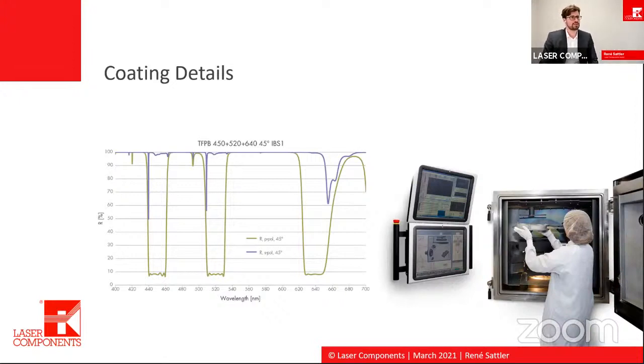We designed the coating for an angle of incidence of 45 degrees, so it's pretty easy for the customer to handle this component. The customer did not want a big displacement of the transmitted beam, so he wants the substrate pretty thin. As we applied an IBS coating with lots of stress, we also had to apply a stress compensation coating on the backside to maintain the good surface figure of the substrate.